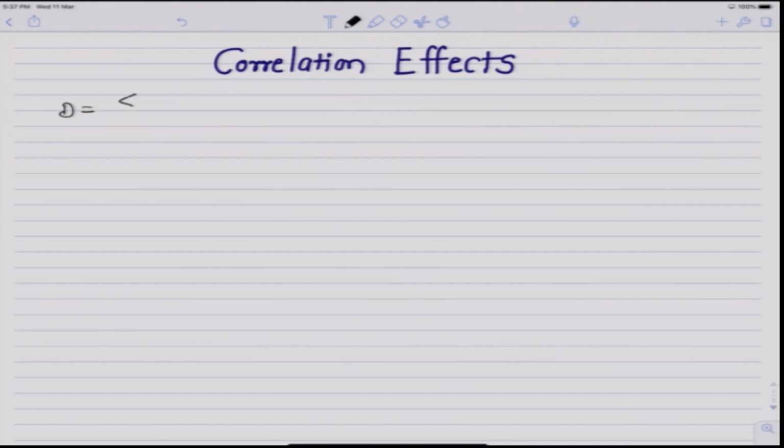Just a recap over the last couple of lectures, we derived the expression for diffusivity in terms of mean square displacement as D equal to average of x square over 2 tau, where x square inside the triangular bracket denotes the average of square of x projections of net displacements of all the atoms, and tau is the small time interval.